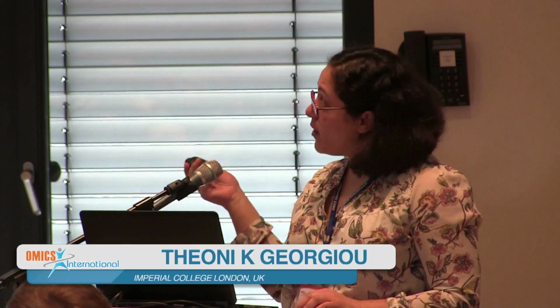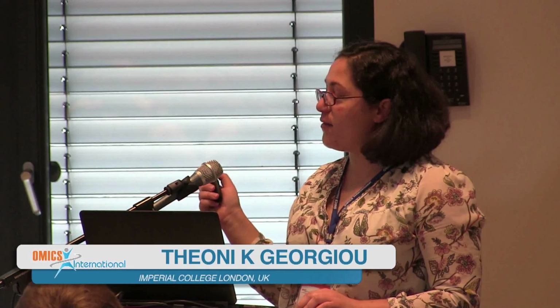GTP was developed by DuPont in the 1980s, and it's not a method that is used a lot now, but the patent just expired, so I'm assuming that this is going to be used a lot more in the future. It is commercially used to make standards, because it produces polymers with very, very narrow polydispersities. The disadvantage is that you can only polymerize acrylates and methacrylates, so you're a little bit limited in terms of the chemistry sometimes. But it does produce polymers with very good control, so well-defined molecular weight distributions, as well as very well controlled in terms of composition and architecture.